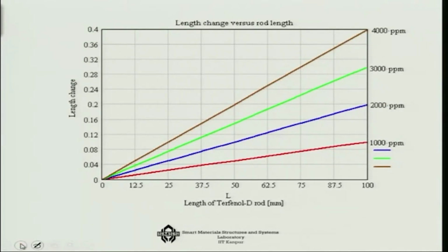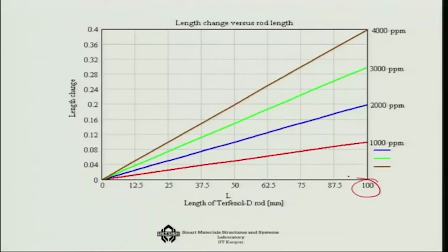Now I told you that magnetostrictive material shows something like 2000 parts per million or a little more than that in terms of the active strain. So how much does it mean in terms of the change in length? Let's say I choose a 100 millimeter beam and I apply this material over it, and the free strain is something like 2000 parts per million. You are going to see that it is slightly lower than 0.2, between 0.16 and 0.2, that's the change in the absolute length that you can expect in such situations from this material. So this gives us an approximate idea of the type of change that you are going to see in this material.